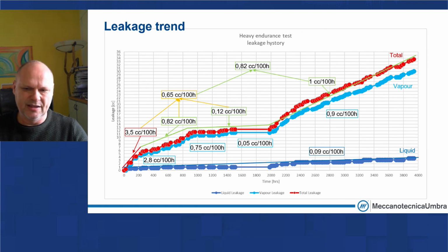The result of the leakage rate in this test for 4,000 RPM, for 4,000 hours, and this means 1 million kilometers for the vehicle, is something like this. So we reach a total leakage in terms of liquid of a couple of cc. We produce an amount of vapor around 25, 26, 27 cc. So the total amount of leakage in 4,000 hours, that means 1 million kilometers, is 33, 34 cc. This leakage must be managed during the life of the motor.